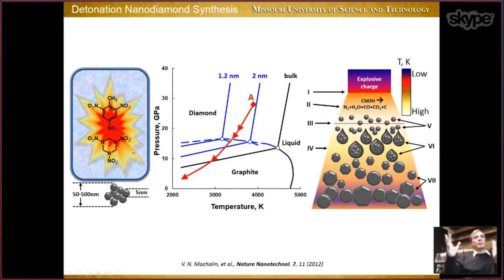Okay, so it's a closed chamber filled with inert atmosphere, nitrogen, argon. Sometimes people even use water. And then you do detonation there. You have very high pressure and temperature, as you can see at this diagram. And the range of pressure and temperature developed during detonation corresponds to the domain of thermodynamic stability of nanodiamonds. So it's this point A here on the phase diagram.